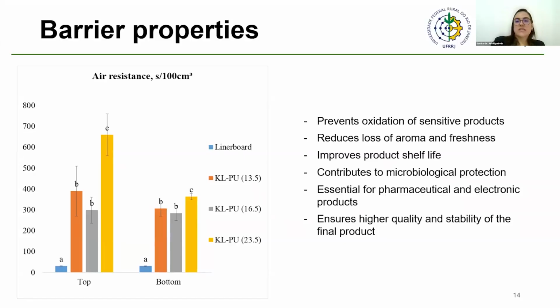And we can see that the barrier performance tests show that air resistance increased with the coating grammage, indicating reduced paper porosity, which prevents the oxidation of sensitive products and reduces loss of aroma and freshness when we think about food and cosmetics. It can improve product shelf life and contributes to microbiological protection. This property is essential for pharmaceutical and electronic products because of the oxidation they can have, and ensures high quality and stability of the final product.